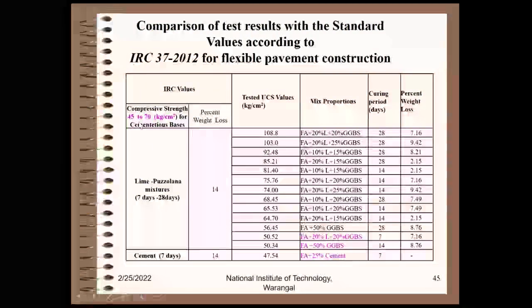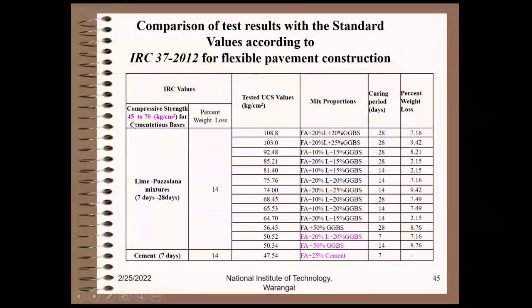And for our road engineering, see the IRC suggests 45 to 70 kg per centimeter square between 7 days to 28 days curing period. For that also, our experimental results for different combinations at different curing periods, we got the unconfined compressive strength within this range, and the percent weight loss, etc., were again satisfied. That is why successful combinations only I have presented here.